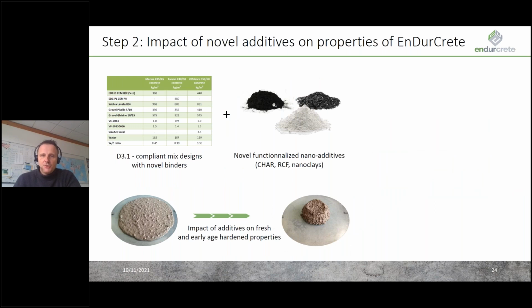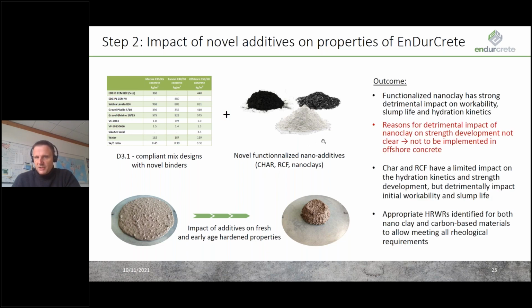Then in the second step, we try to incorporate these novel additions and additives into existing concrete compositions. But before we did that, we try to figure out what's the impact of these additions on fresh and hardened properties of the concrete. The focus was on workability and strength development, and we try to incorporate a nanoclay corrosion inhibitor and 2 types of carbon-based materials, char and recycled carbon fines. And the study on the compatibility of these additives with the concrete was done by Sika, and what they figure out is that these additions have